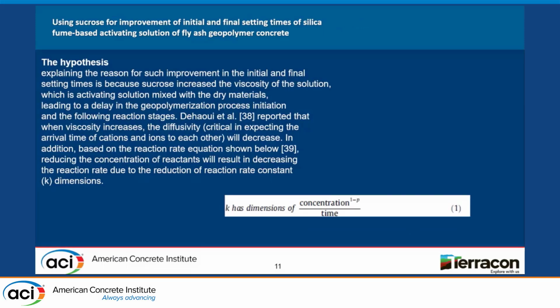And here is our hypothesis for why we have this improvement, especially in the extension of the initial and final setting time. We believe that adding sugar increases the viscosity, and viscosity makes it hard for the particles to move from side to side. So the particles or the ions take longer to move from side to side to make the reaction, which leads to the delay in the reaction.